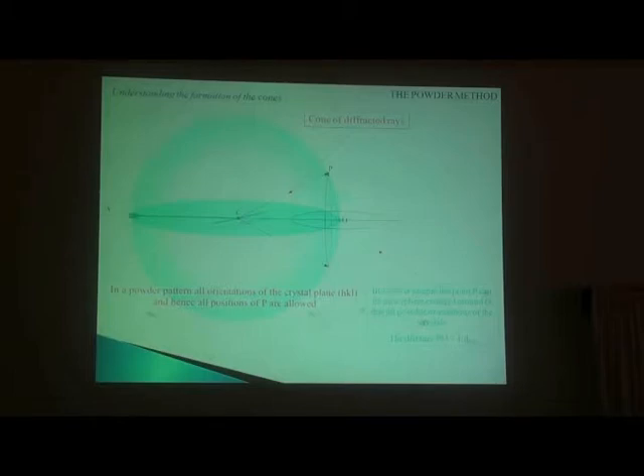Look at this, in a powder pattern you have very minute crystallites oriented in all possible random directions, in all orientations of the crystal plane. The size of the crystallite is very small, that's the only difference. But it is oriented randomly in every direction. That means at every theta, you have some planes giving you scattering. You get a scattered vector. So the locus of the vector OP, what is it? It's a sphere of radius OP over reciprocal space. Agree?